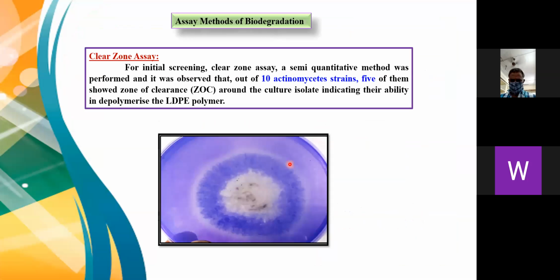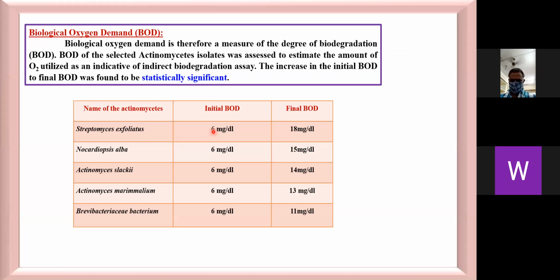Next, assay methods of biodegradation: the clear zone assay. For initial screening, the clear zone, a semi-quantitative method, was performed, and it was observed that out of 10 actinomycete strains, 5 of them showed a zone of clearance around the culture isolate, indicating their ability to depolymerize the LDPE polymer. Biological oxygen demand is therefore a measure of the degree of biodegradation.